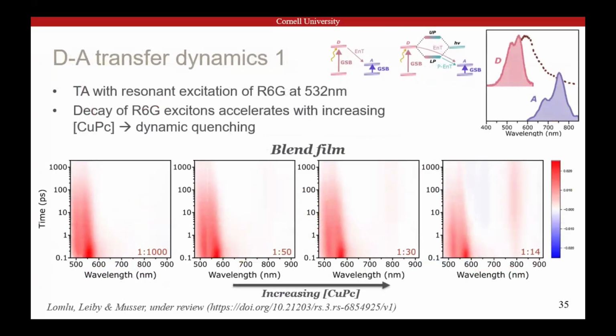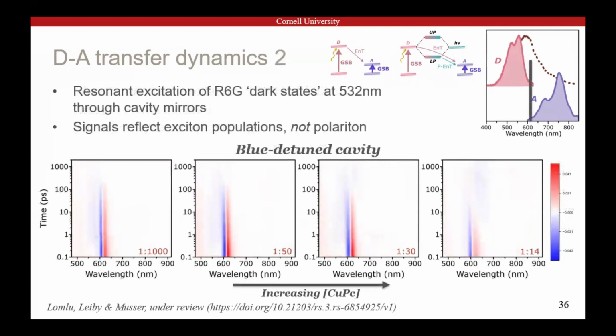So very quickly, we did a lot of transient absorption in our films and cavities. What I'm going to plot is increasing acceptor concentration from left to right. And as we increase the concentration in films, we see the rhodamine signatures decay faster. We start to see acceptor signatures turn on. So basic donor-acceptor transfer. And now we can put them into cavities, which look really jazzy.